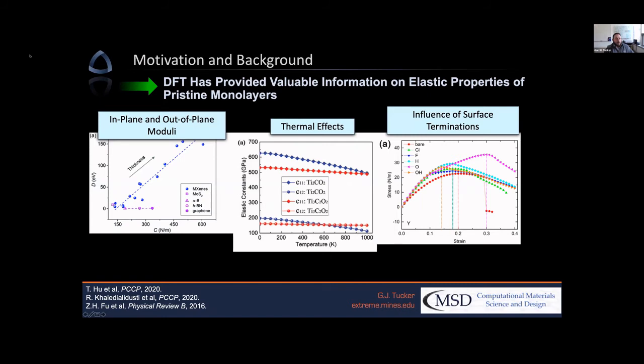Like I said before, there's no way that we can sufficiently summarize all the great work that's been done with DFT over the years, but it really has provided a lot of valuable information on the elastic properties of pristine monolayers for the most part. Shown on the left here are both in-plane and out-of-plane moduli, comparing calculations of MXenes to other common 2D materials which have been studied. In the middle here, we can see the effect of temperature on elastic constants, specifically looking at the titanium carbon based MXenes with oxygen terminations. And then on the right, what's the influence of surface terminations in regard to the stress-strain response of MXenes?